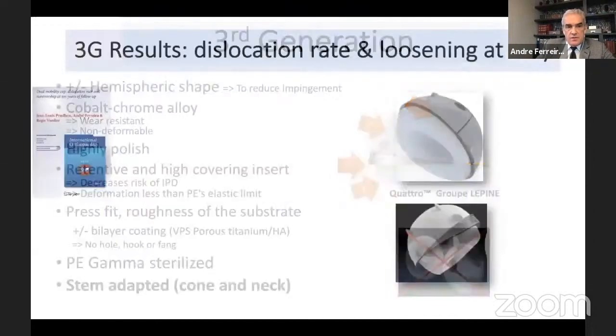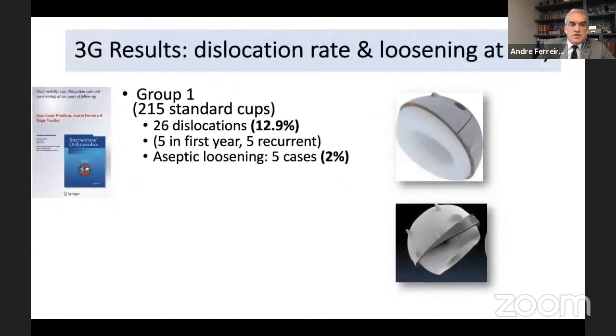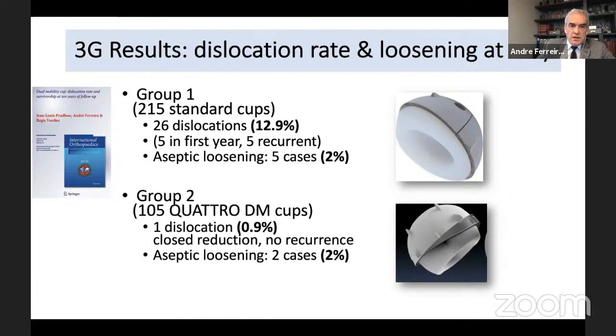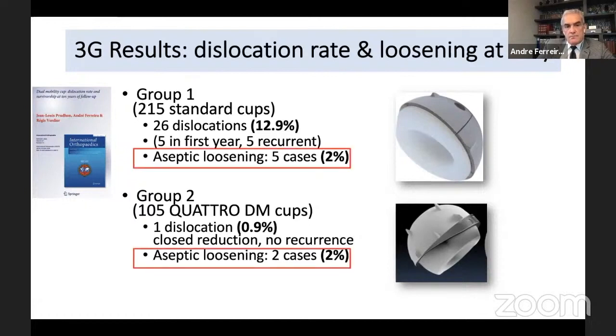For this third generation, we have published some results comparing standard cups at 10 years and a dual mobility cup, the Quattro one, and we can see that the rate of dislocation is very different, from 13% to 1%, and the risk of aseptic loosening is exactly the same. So we have better results against dislocation with the same longevity at 10 years between standard cups and dual mobility ones.